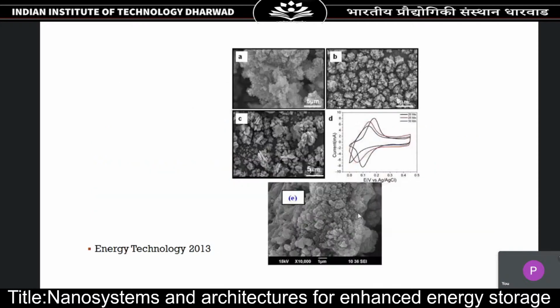So these are some high magnification SEM images of the composite structure. You can see that the cobalt hydroxide is in a flaky form, and on top of that we deposit the graphene. So we were able to get a porous structure and a porous multi-layered structure.